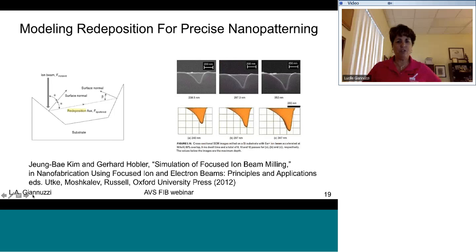Here's some work by some authors that actually simulated focused ion beam milled features by incorporating a redeposition model and where the sputtered stuff goes, so that they can accurately predict what kind of shapes you'll ultimately get. Prior to this, people would basically do trial and error types of features. I want to mill this Fresnel lens, I want to mill this whatever feature, and then ultimately not get what they were hoping for, tweaking things on the fly. If you incorporate the redeposited material from sputtered particles into a model, you can actually reproduce this quite well and predict what your features will look like.